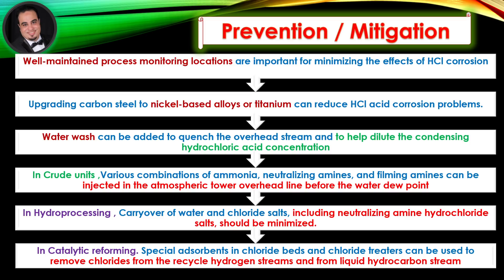Before the water dew point. In hydro processing, carry over of water and chloride salts, including neutralizing amine hydrochloride salts, should be minimized. In catalytic reforming, special adsorbents in chloride beds and chloride treaters can be used to remove chlorides from the recycle hydrogen streams and from liquid hydrocarbon streams.